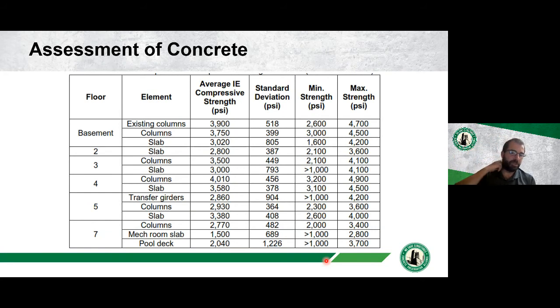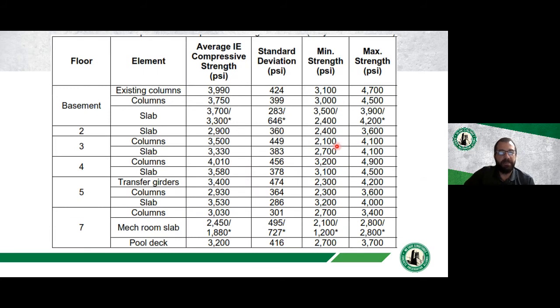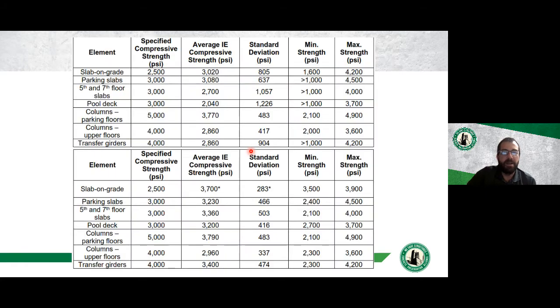And so we went through the structure and measured the compressive strength on various elements, on columns, slab, girders, and different things like that. And so we can see what the average compressive strength is here, the deviation, and then min-max. But it's important to know, obviously, that damage in the concrete will affect this measurement because this is an in-situ measurement. And so here again, we have more measurements, we can pull that together.